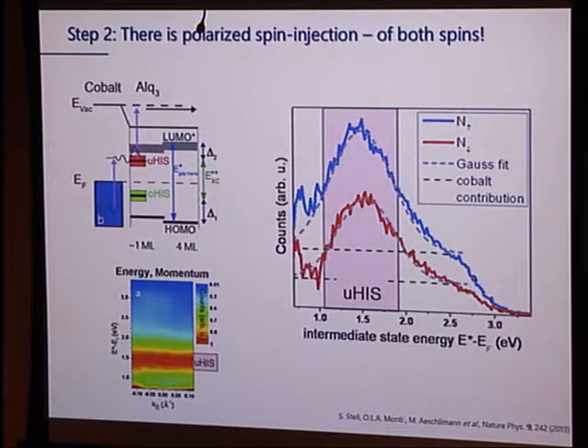The second step is to see if that interaction leads to spin polarization of some sort, meaning that we have an imbalance in some way or form of spin density for spin up and spin down. So we first did a momentum-resolved photoemission spectroscopy of these interface states to see that they do not disperse at all. So the band structure is flat, and that's a hallmark of it being molecular in character. Right? If this was cobalt, it would be dispersive in some form or fashion. So this is telling us, indeed, this is a state that carries molecular character.